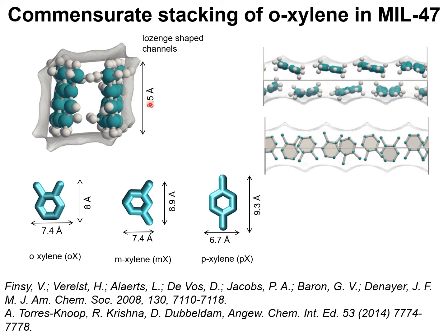Within the 8.5 angstrom sized lozenge-shaped channels of MIL47, we achieve a commensurate stacking of orthoxylene. If we look into the channels, we see face-to-face stacking of orthoxylene.